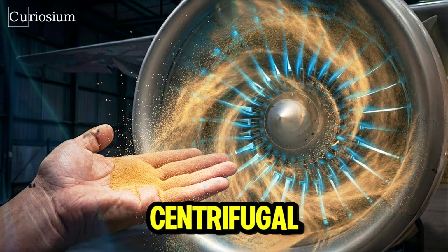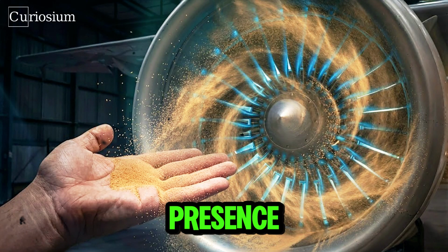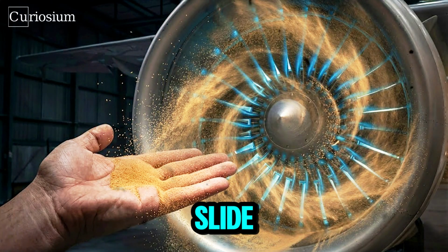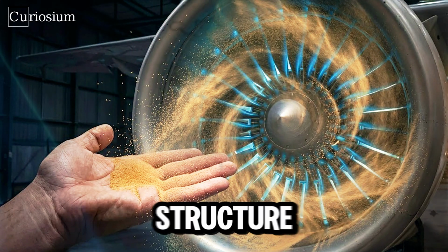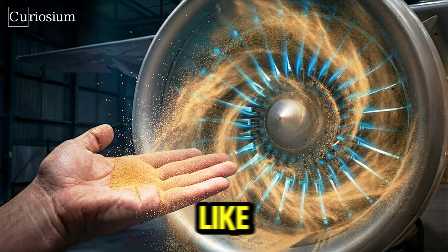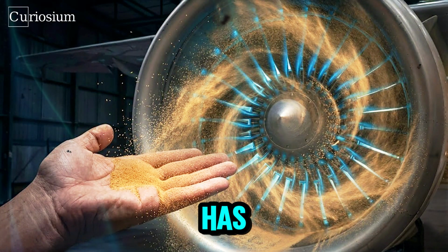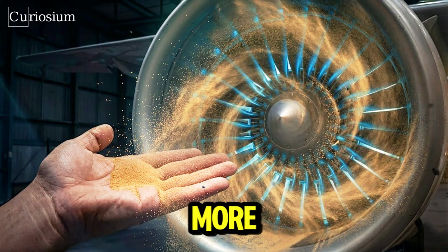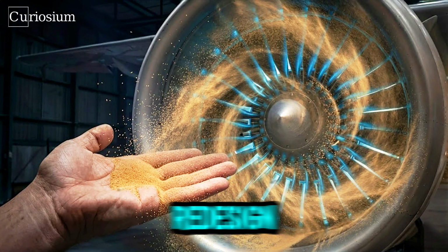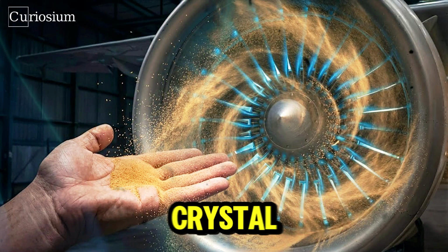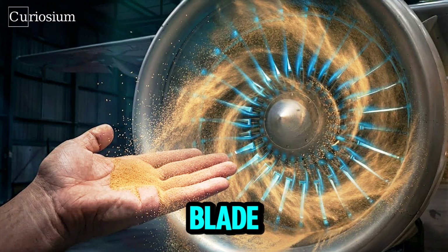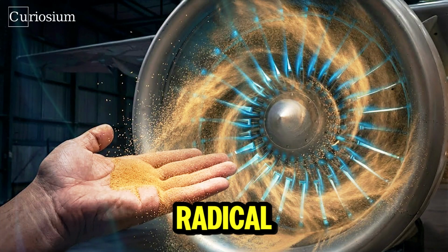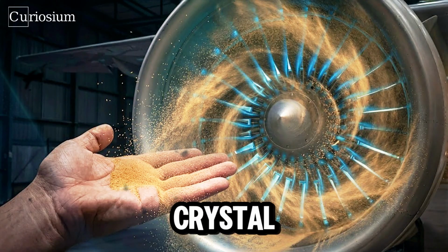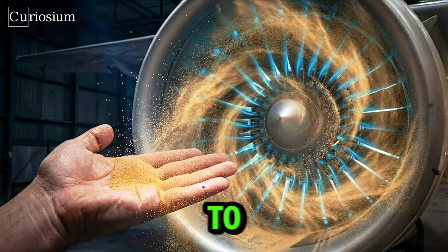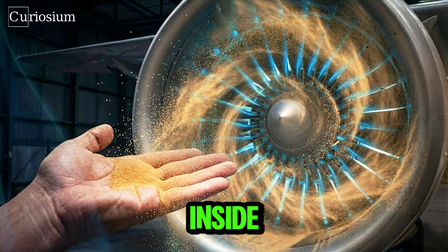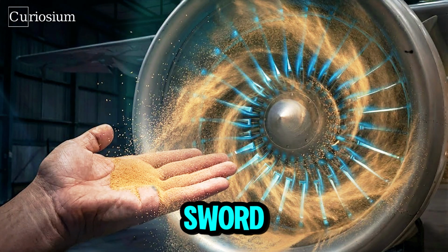Under the enormous centrifugal loads on a turbine blade and in the presence of high heat, grains can start to slide along those boundaries. The whole structure can slowly deform like soft candy. As long as a metal has many grains and many boundaries, it will creep more easily. So engineers did not just redesign the alloy. They redesigned the crystal structure at the scale of the entire blade. The goal was simple and radical. Grow each blade as a single crystal, one continuous lattice from root to tip, with almost no grain boundaries inside it. How you grow a metal crystal sword.